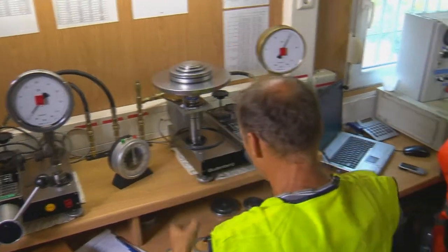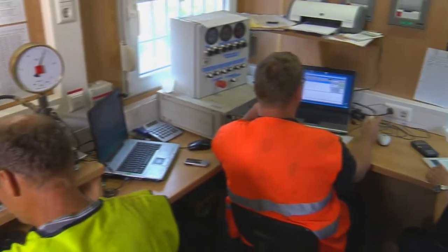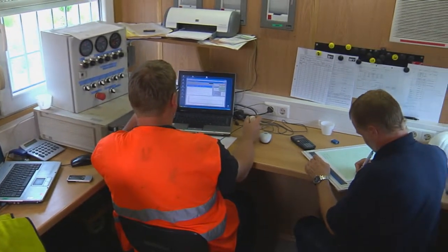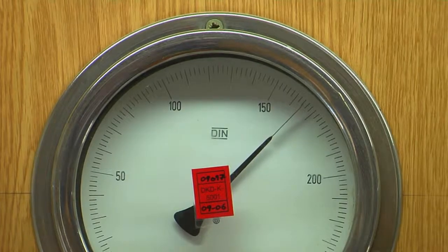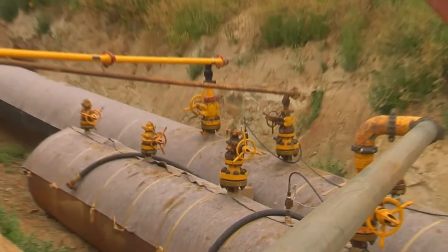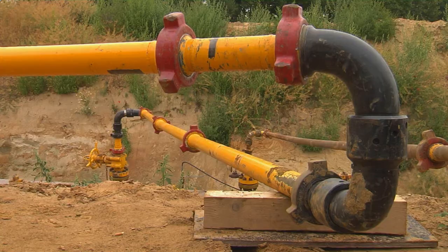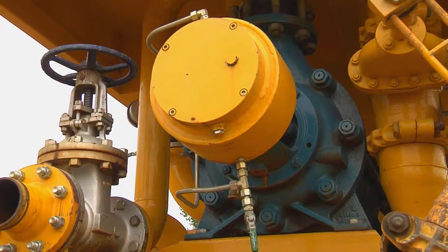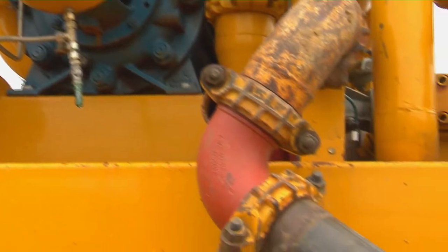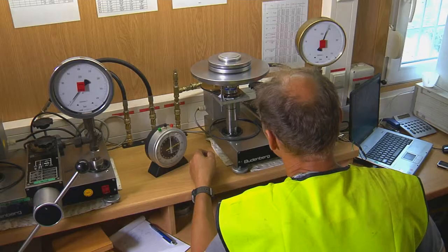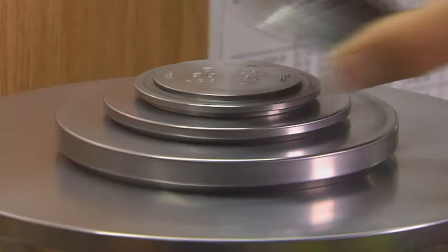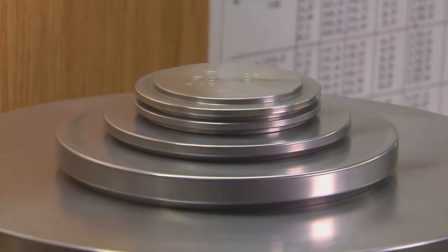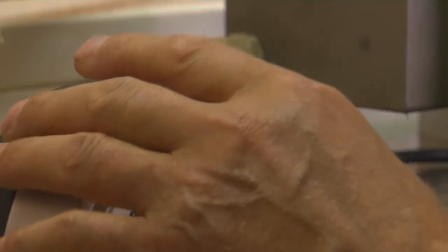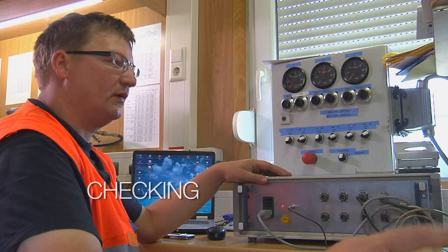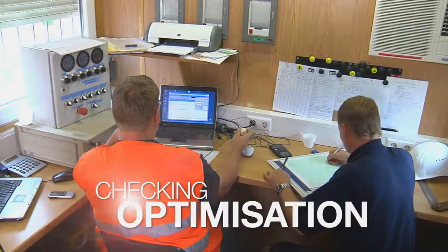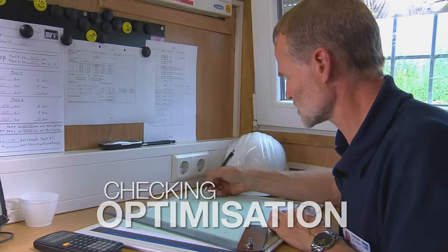In the stress test, it is primarily the welding and laying stresses that are reduced. Our expert appraiser continuously records all the measurements taken. As a genuine strength and endurance test, the procedure stresses all OPAL's pipes up to almost the actual yield point. The stress test is at present the only test procedure that itself rejects hazardous defects. In contrast to most other test procedures, the stress test serves both to check and also to optimize a pipeline. This enhances the operational dependability and cost efficiency of the pipelines tested.